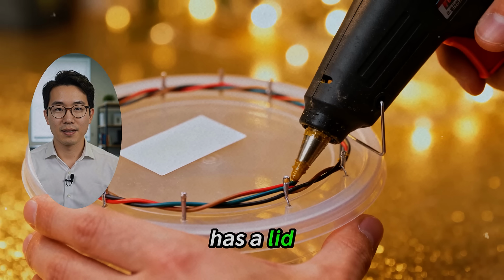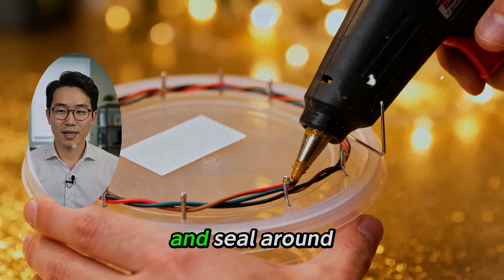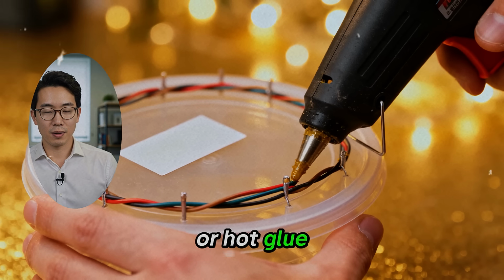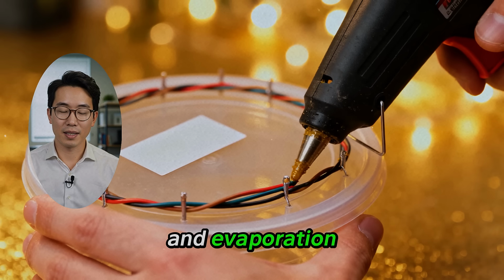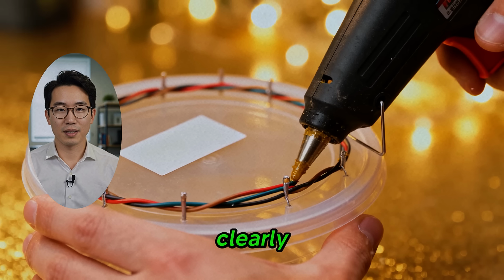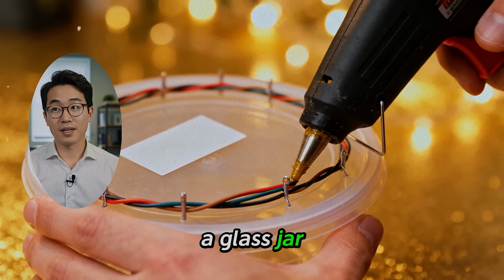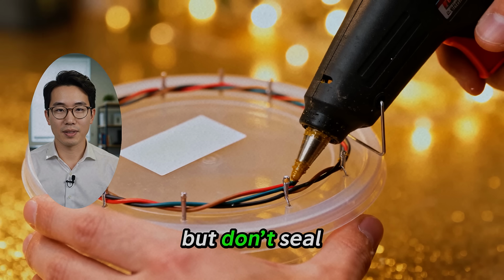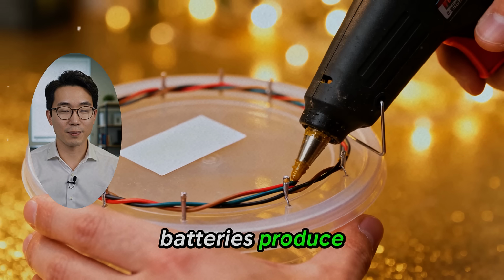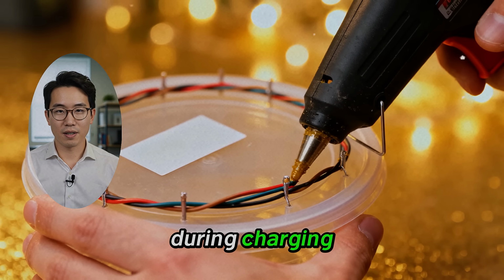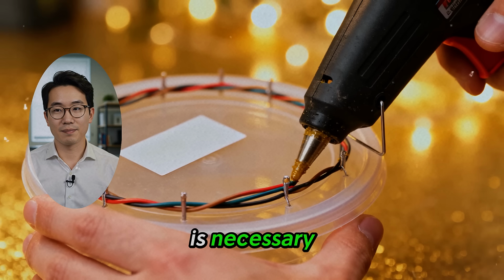If your container has a lid, drill small holes for the wires and seal around them with silicone or hot glue to prevent leaks and evaporation. Label the positive and negative terminals clearly. If you're using a glass jar, you can simply rest the lid on top, but don't seal it airtight. Nickel-iron batteries produce a small amount of hydrogen gas during charging, so some ventilation is necessary.